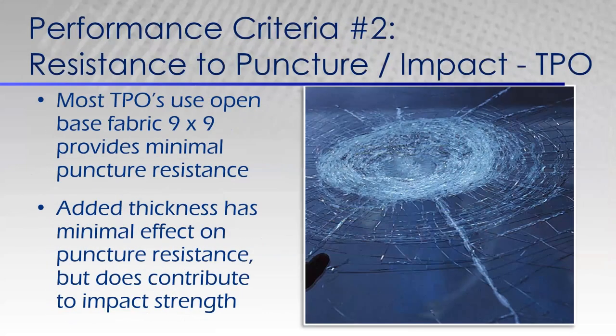Let's talk about TPO. So when we look at TPO on the roof, it also has that open 9x9 weave, which gives you puncture resistance. It reinforces the strength of the membrane, but it's not as dynamic as what you would see with a tighter weave product. So what this means is, same thing we saw with EPDM, the thickness does contribute to the impact strength, but has very little effect on puncture resistance of the product on the roof. And how many of you have been on a roof when they've dropped tools and screws and walked on those on the roof and you can see micro tears and tears on the roof before you even finish the project? Resistant nature of your TPO.